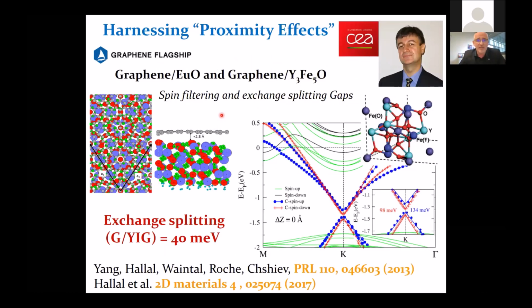Early on, Manuel Bibes from CEA pioneered the ab initio DFT simulation of graphene deposited on a magnetic insulator, which could gain some magnetic properties. He actually demonstrated that a very giant exchange coupling will be generated by YIG. So YIG is a very interesting high Curie temperature material. So this was in 2013.